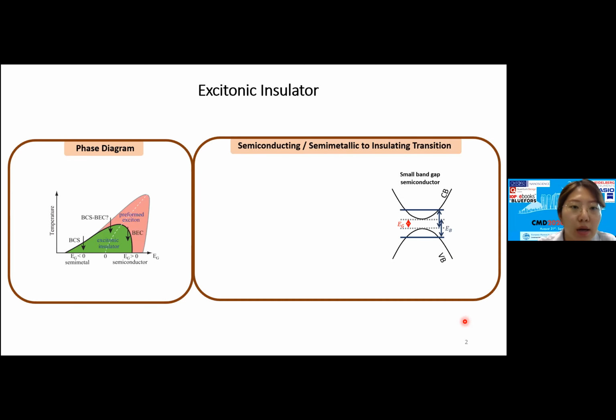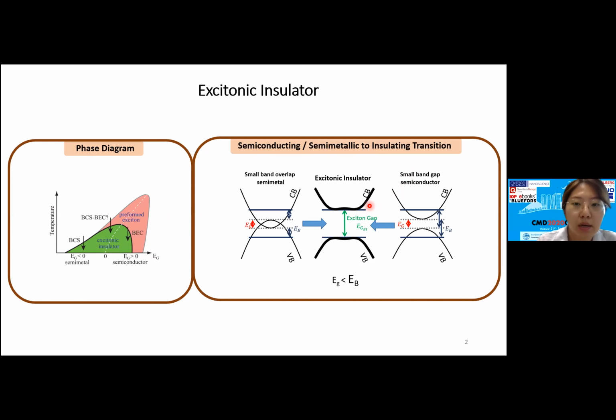Excitons are bosons and can condensate, and theoretically we can expect this phase diagram. When the semiconductor has a very small band gap energy, even smaller than the excitonic binding energy, it starts to condensate, and a gap is opened. This also happens on the semimetal side. We are going to study tantalum nickel selenide, which is a zero gap semiconductor system that has a transition temperature Tc of 328 Kelvin.